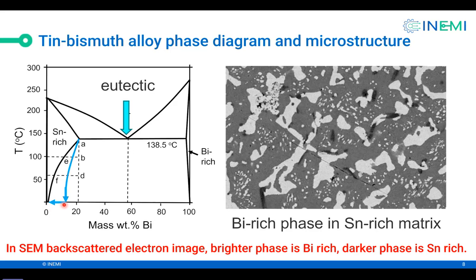It contains too much bismuth. So the tin-rich phase contains, let's say, 10% bismuth. At room temperature, it will approach equilibrium over many weeks and get to, let's say, about 2% bismuth in the tin, and that's when you get these fine precipitates of bismuth. So we have the large precipitates of bismuth just below eutectic, and at room temperature aging, you get the fine precipitation of bismuth. So that's just introduction to this alloy.